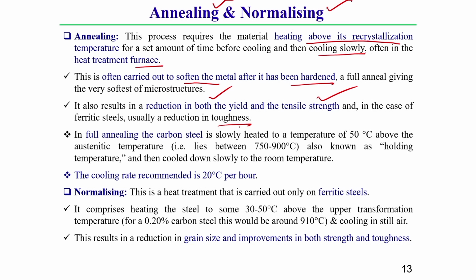Here one thing you should keep in mind: in full annealing of carbon steel, we slowly heat to a temperature of about 50 degrees above the austenitic temperature, that means within a range of 50 degrees centigrade above the austenitic temperature. After that we hold this temperature for a particular time, which is why it is called the holding temperature, and then cool down slowly to room temperature.